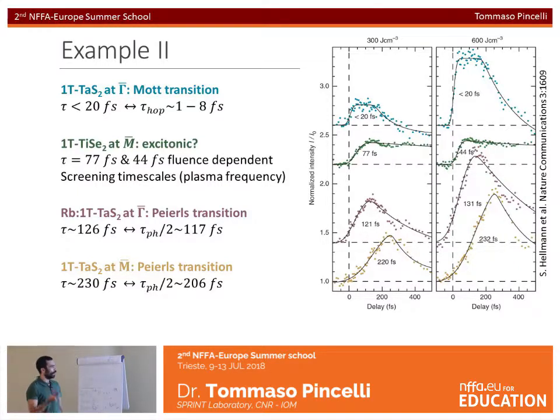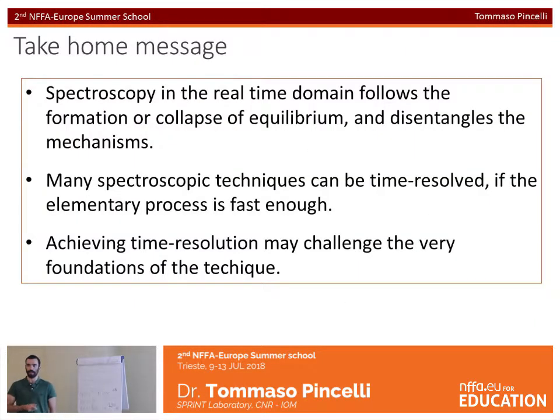So with this, I point out the take-home messages that I wanted to deliver. It's the fact that spectroscopy in the real-time domain follows the formation or collapse of equilibrium and disentangles the mechanism, allowing you one more tool to disentangle the mechanisms. And that you have many spectroscopic techniques that can be time-resolved, but you have to take care that the elementary process is fast enough. And finally, achieving time resolution must be done, once again, with reason, by thinking, because this may challenge the very foundations of the technique, as we said.